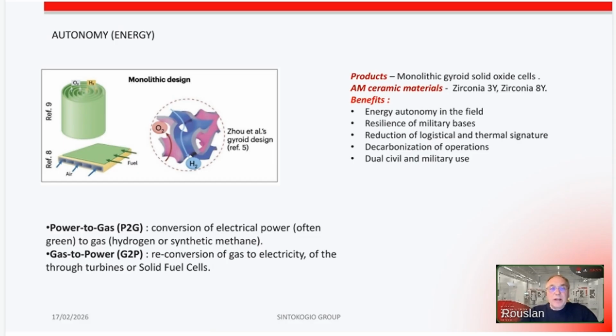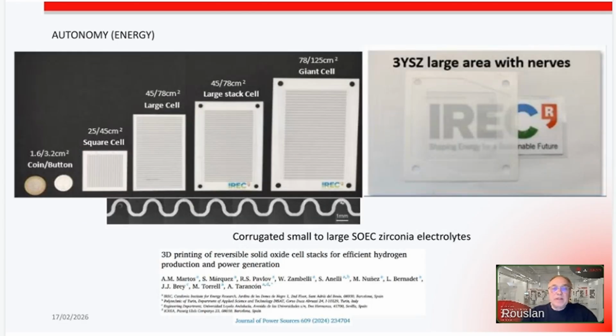A lot of people are working there, and we have some good materials like zirconia 3 yttria, zirconia 8 yttria with high ionic conductivity. Again, combined with some specific honeycomb or gyroid structure, it can give good results for these kinds of devices. It's not yet an industrial solution, but the studies are well advanced, and the TRL for some of them is rather high. So we have good experience in this as well.